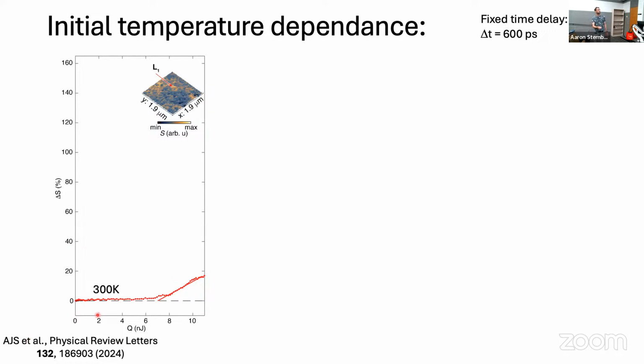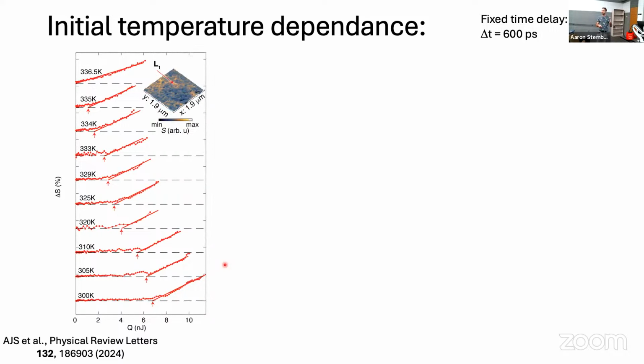So first, starting from room temperature, what we're looking at is how the signal changes at a single location. As a function of fluence, we see this nice sharp threshold. And as we increase the base temperature, so we're starting at this base temperature and then we're increasing the fluence and watching how the system changes, we can see this nice systematic decrease of the fluence threshold with increasing base temperature. All of this is at a single fixed location.